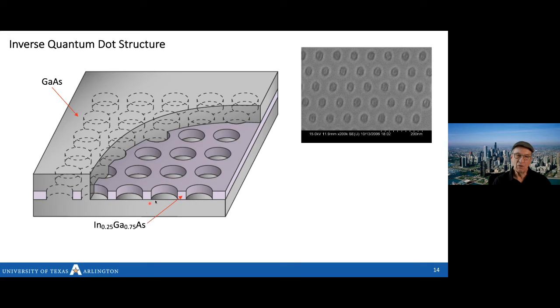We take gallium arsenide, grow this first layer, stop and put some holes in it, and then grow some material on top of it. So basically this layer is a Swiss cheese or perforated InGaAs layer at lower energy, completely surrounded top, bottom, and through the pores with higher confining energy material.